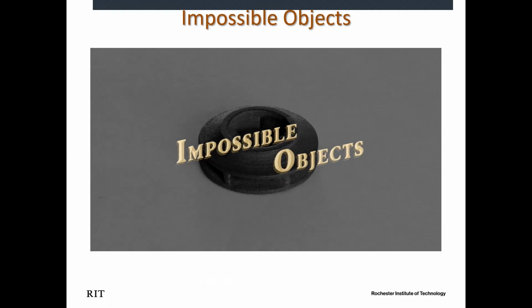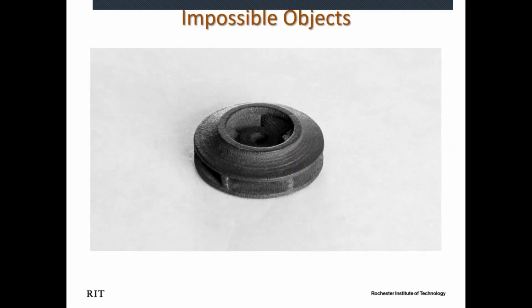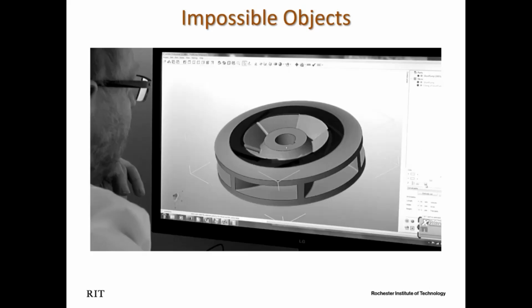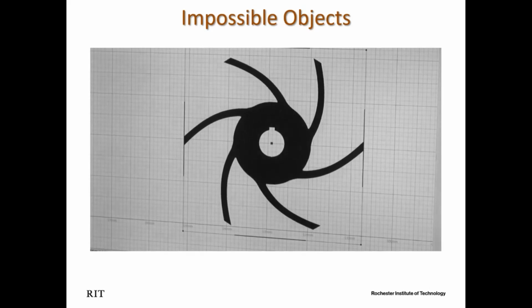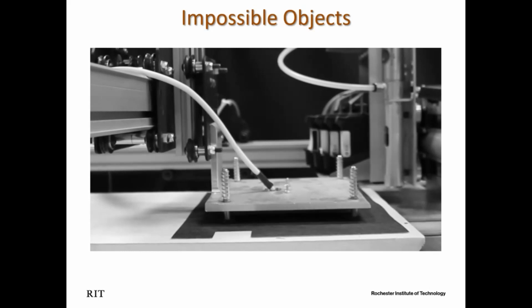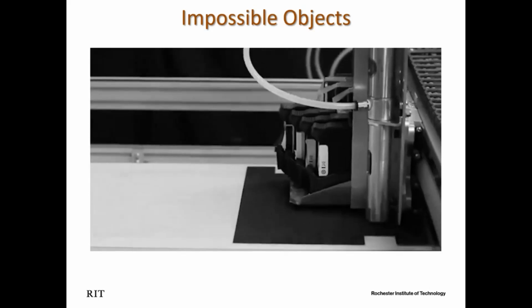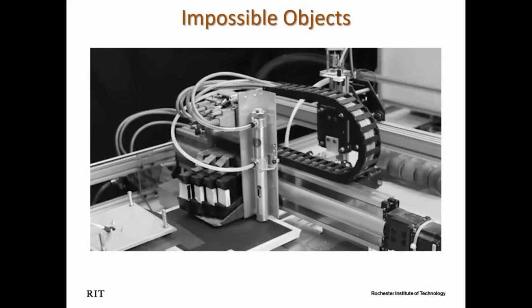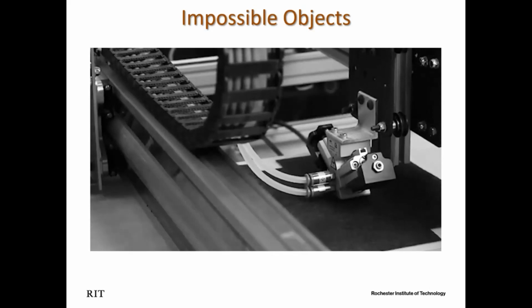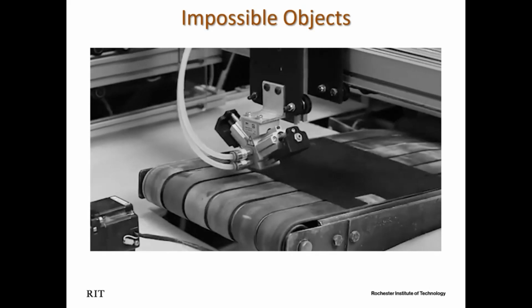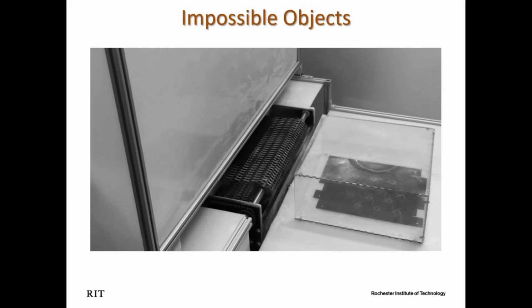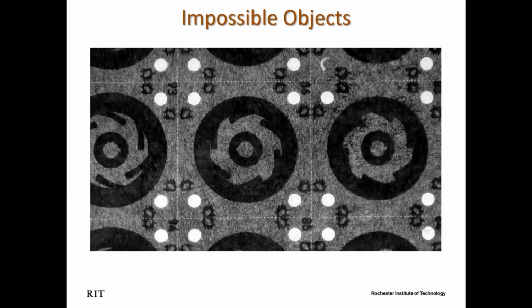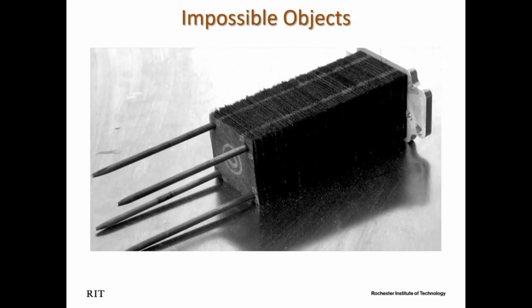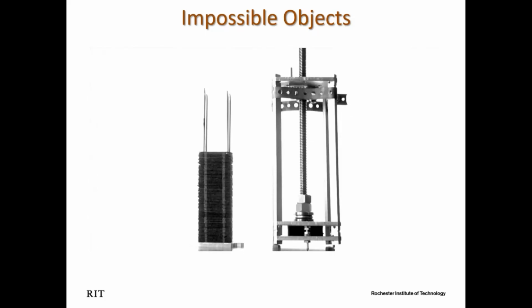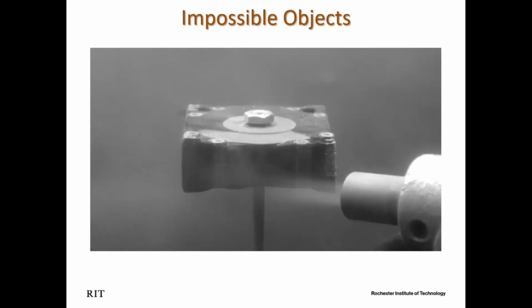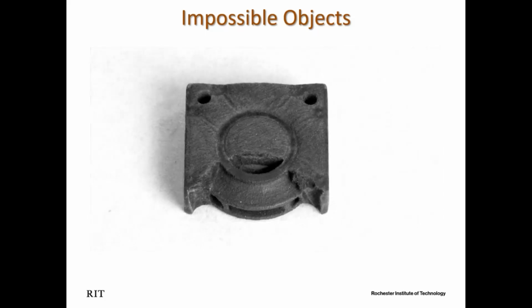Impossible Objects technology enables additive manufacturing of fiber-reinforced composites for making production parts. The CAD model is sliced into layers, and each layer is converted into a digital bitmap. Layers are printed onto fiber sheets using a clear fluid and thermal inkjet technology, and a high-precision positioning system guides the inkjet heads. Polymer powder is applied to the fiber sheet, adhering to the printing fluid. Excess powder is removed, leaving behind polymer in the shape of the bitmap. This process is repeated for all of the layers of the part. Sheets are stacked, heated to melt the polymer, and compressed to consolidate the part to its designed height. Through a mechanical or chemical process, the uncoated fibers are removed, revealing the part.